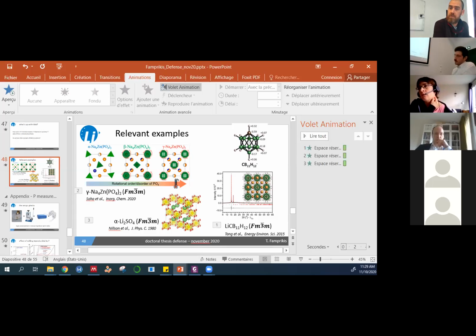There is no relationship that I could find with anything tetragonal or cubic or any distortion of them. And it goes back to the same point. Even if I lower the symmetry further, we go into this point of why do we keep reducing the symmetry, even though we're looking at a very disordered high temperature phase? So the two points are a bit in contrast to each other.